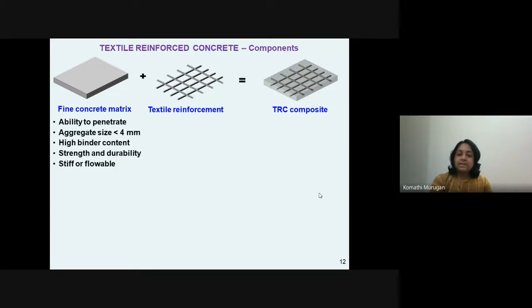So what we look at, 0.5 or 1 mm. So what we look at is a concrete which has an aggregate size of less than 4 mm, and right now what we look at is an aggregate size of around 0.8 to 1.2 mm for textiles of grid dimensions up to 2 to 2.5 centimeters. So the aggregate size is too small, and we call it a fine grained concrete. This concrete essentially has a higher binder content for better flowability properties and to get better strength and durability.